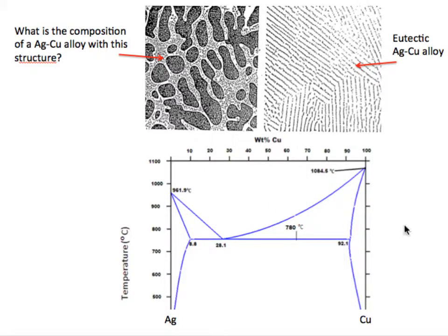The next step is now to make an evaluation of the volume fractions of the two structural components. That is, how much primary precipitation, how much copper dendrites do we have, and how much eutectic do we have. That can be made in different ways. You can make a line analysis. You can also use an image analysis system in the microscope. If we assume that we do that, we will find that we have 60% dendrites and 40% eutectic structure. So that will be the background for the calculations we will continue with now.